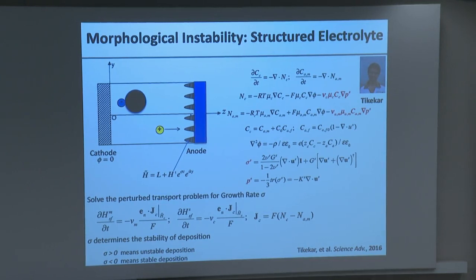So we did the same thing as before. We write down, again, the conservation of mass equations, and this is the flux. The flux has basically three terms. There's a diffusion term. There's an electromigration term that goes like the potential difference. And there's a so-called pressure diffusion term, which was not known before this work. The way this pressure diffusion term works is actually pretty simple. So it works as follows.